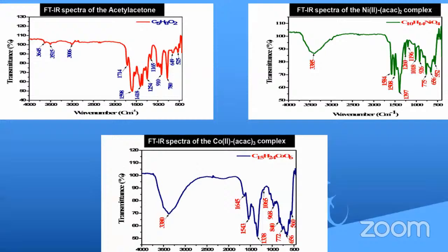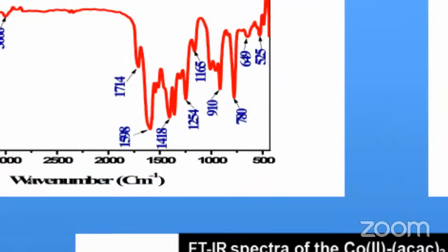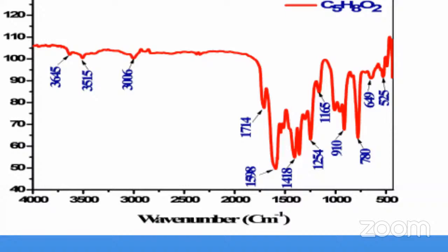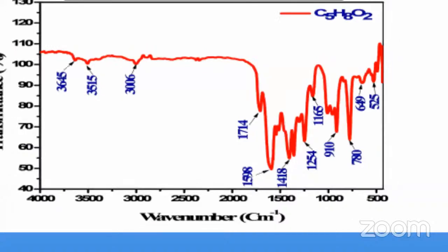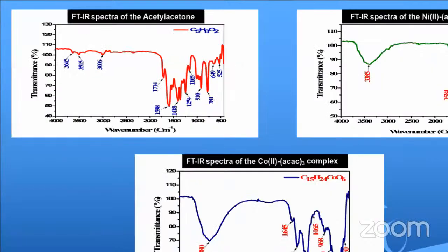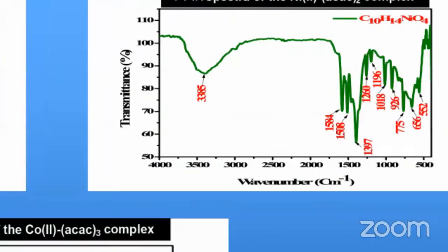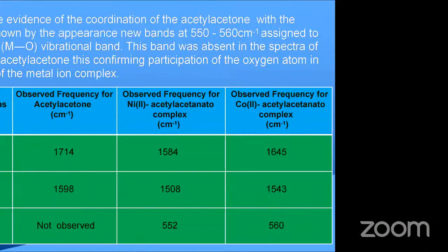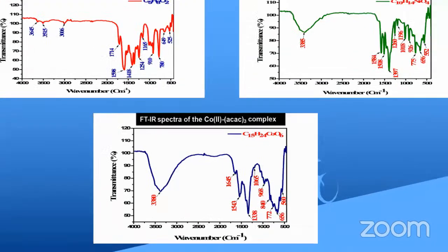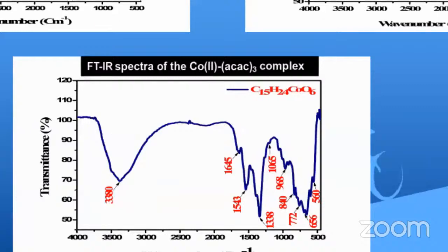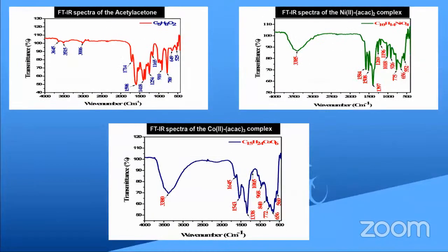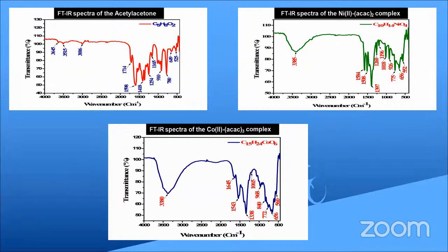The FTIR spectra show 1714, which is due to the carbonyl group of acetylacetone. Here the shift will be at 1584 in the nickel complex, and in cobalt it will be at 1543 centimeter inverse, which confirms the complexation between the metal and the oxygen of the acetylacetone complex.